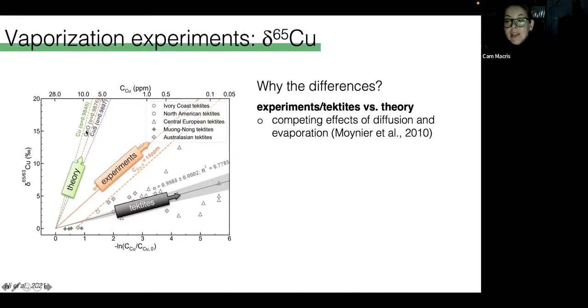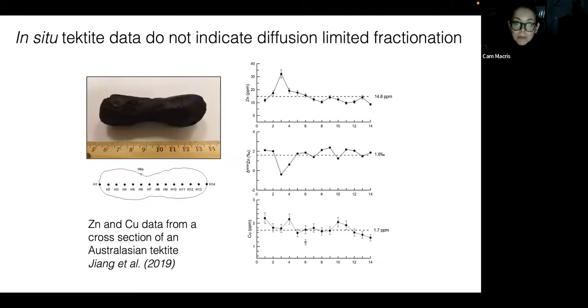One idea is that there could be a diffusion limitation that is suppressing fractionation in the experiments and the natural samples. So in other words, if diffusion of copper from the interior of the melt to the surface can't keep up with the evaporative flux at the surface, what we could see is that there would be less fractionation. However, in a 2019 paper by Jiang and colleagues, they did in situ measurements of zinc and copper on a tektite cross-section, shown here, and they observed no systematic differences or zoning within analytical error. So these data do not support the idea of diffusion-limited fractionation.